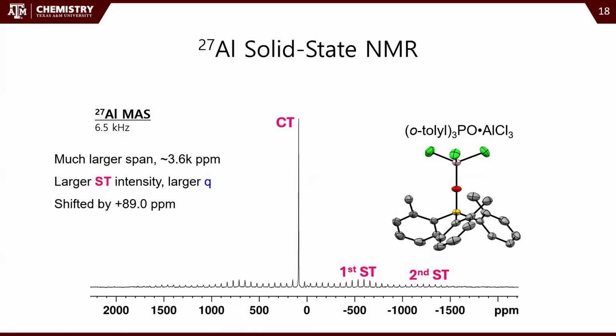And if you want to characterize the quadrupolar interactions, there's some deeper analysis that we didn't really care to go into. Also, it can be kind of difficult because the satellite transitions aren't so sharp. They're kind of broader. So we didn't look into characterizing the quadrupolar interactions more than just looking at the span. Also, the central transition shifted up by almost 90 ppm. So that was surprising. It was a lot more than I thought it would be.